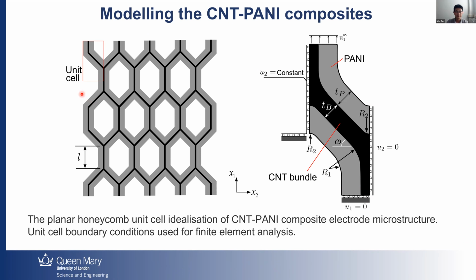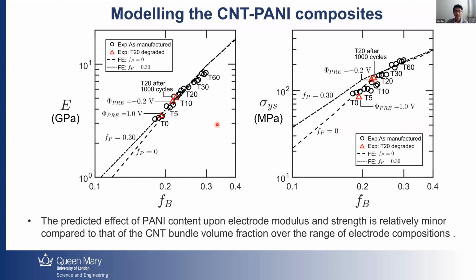So essentially, we actually model this material as a honeycomb network where a layer of PANI is just attached on the honeycomb backbones. And if we simplify the structure, just take a unit cell of this network, we can apply periodic boundary conditions and vary the content of the PANI and also the CNT so that we can vary the CNT volume fraction, the PANI volume fractions, and try to model the mechanical behaviors.